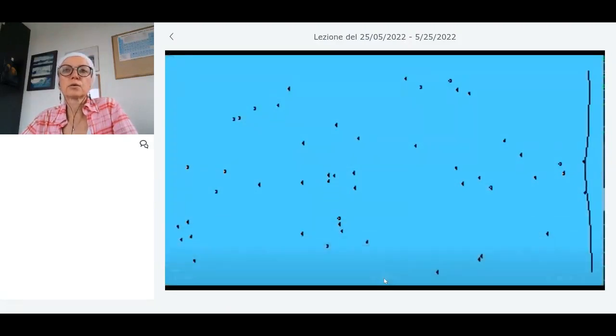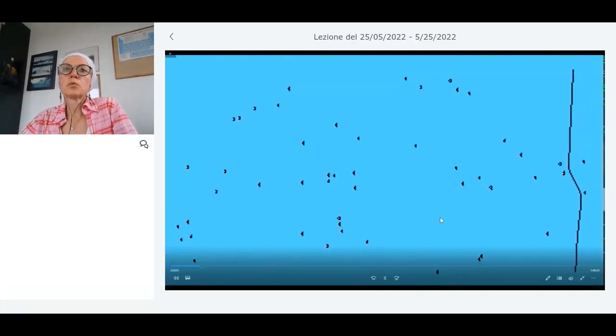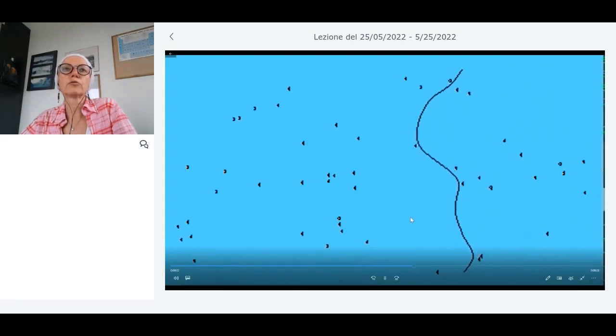Now let's go, and you see that the domain wall will behave like this. It might, for example, stick for a long time at the defect, and then it will go on. And then it sticks again in certain points at the defect, and then it goes on. Of course, this is while you're increasing the field, and you have this domain wall bowing very often. So this is the avalanche-like motion of a domain wall.